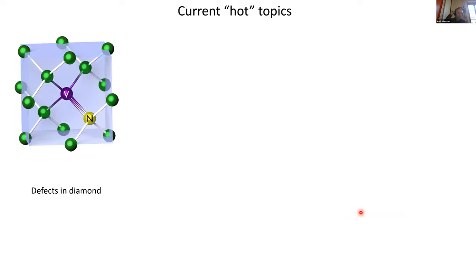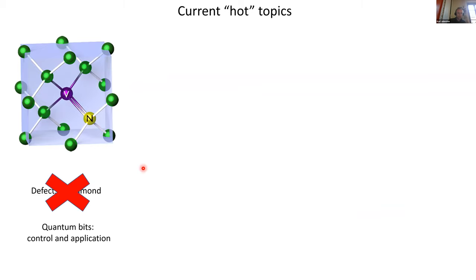Here is a diamond crystal with a carbon replaced by a nitrogen atom, and a V which means a vacancy — a carbon atom has been removed. This is the nitrogen vacancy centre in diamond. When I was doing my PhD we used to call these defects in diamond, but now they've become quantum bits, because it was realised about 15 years ago that the nitrogen vacancy centre has promise as a quantum bit for future applications involving spintronics, metrology, and very sensitive sensing applications.